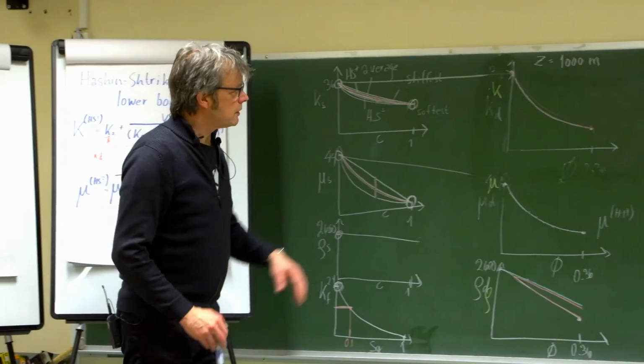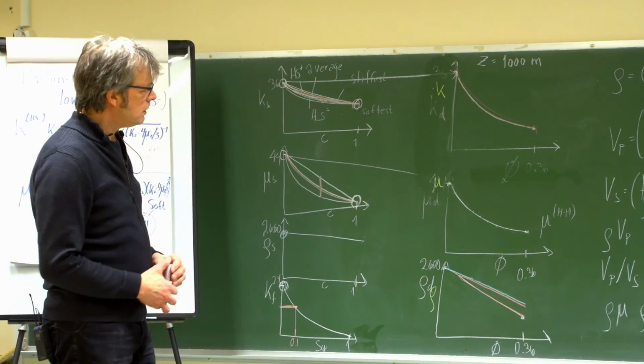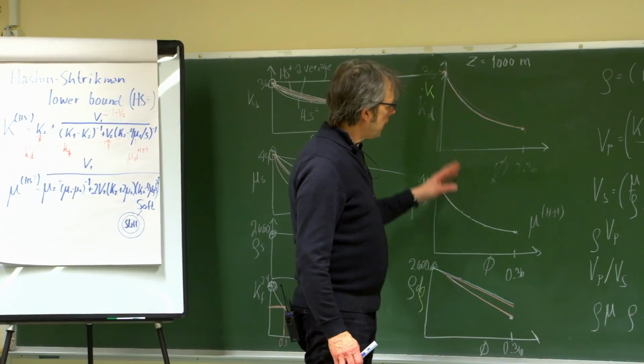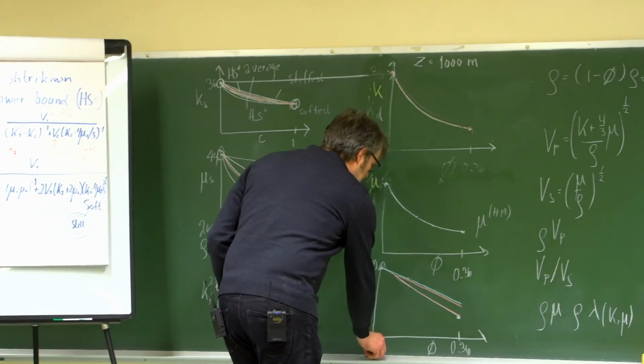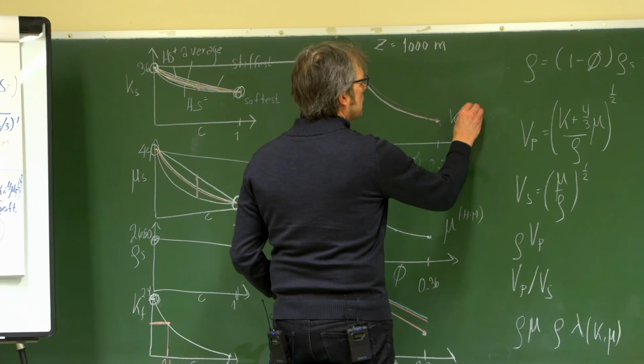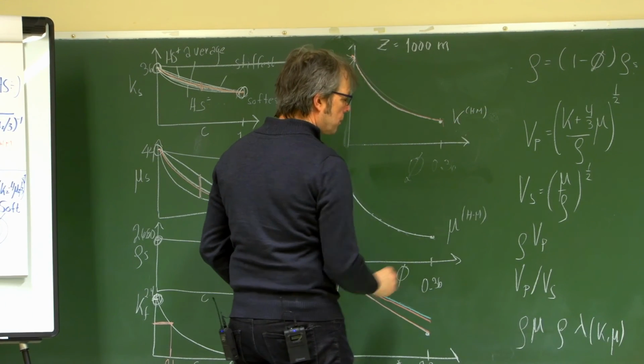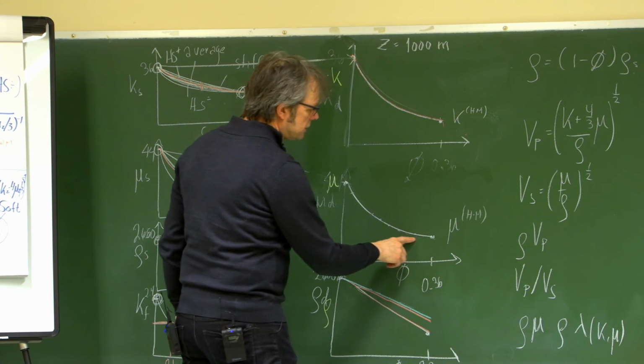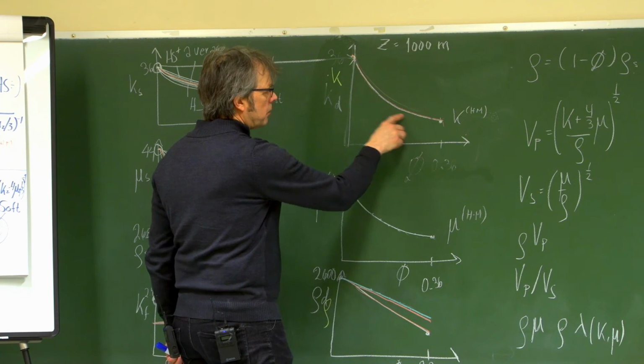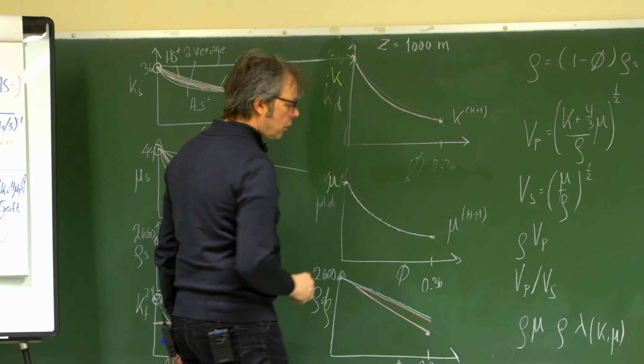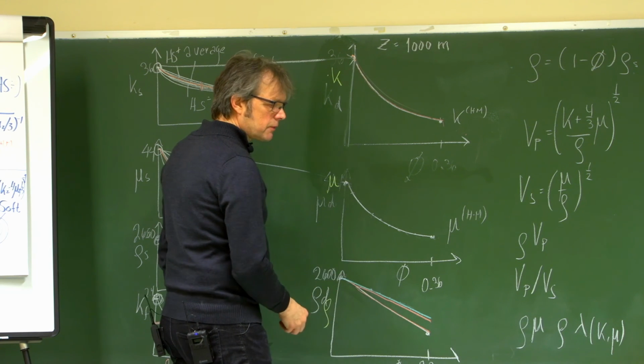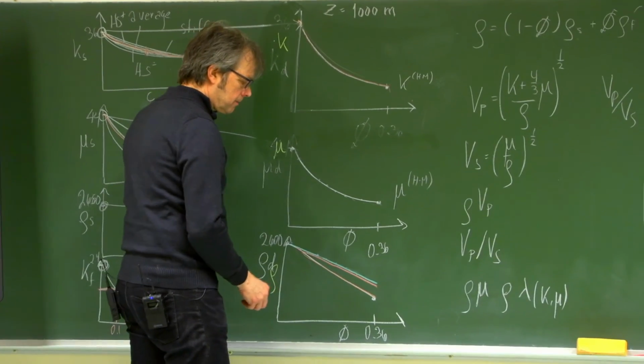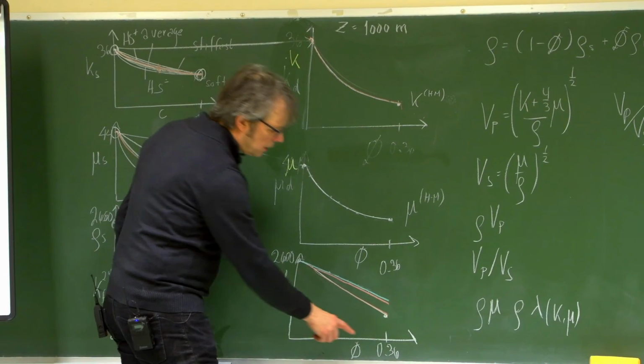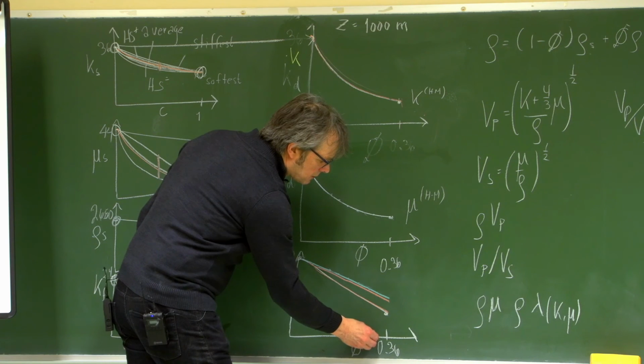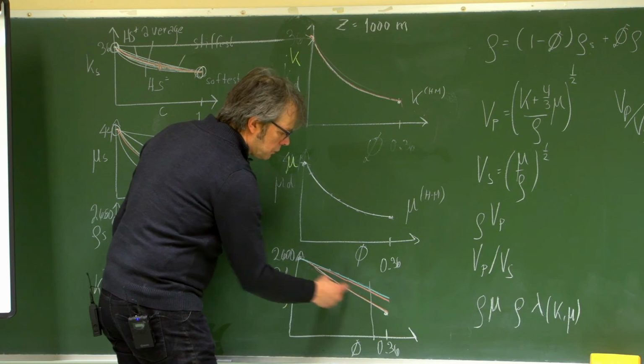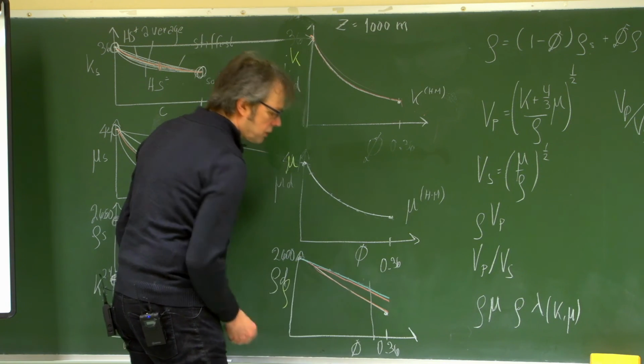I just cleaned up some of the drawings, but I have some reference here just for you to know. We go back here. I had the Hertz-Mindlin point here for the bulk modulus and for the shear here. And then I did this interpolation using the lower Hashin-Shtrikman bound. So these are the dry rock properties at 1 kilometer depth. Density would behave almost the same, so I will just let it remain as it was. Of course, when we start to compact, we have a reduced maximum porosity, so you just need to compute for a lower porosity range.